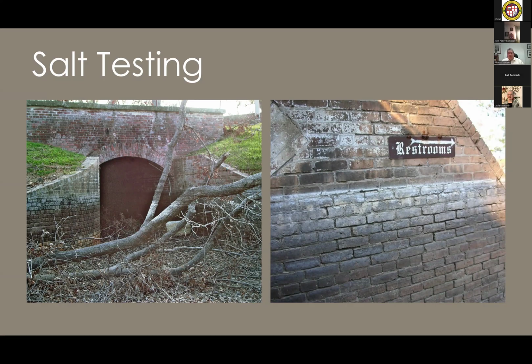This is Fort Jackson, which also got hit by Hurricane Katrina. I looked at about four or five historic forts in Louisiana. But this is after the waters went over the levee at Fort Jackson. The water stayed pretty much at the top, and it went down to about the halfway level, and then stayed there for six weeks. So we ended up with this sort of bathtub ring of salt around the entire fort. And then that salt started to contribute to damage to the masonry and loss of mortar.